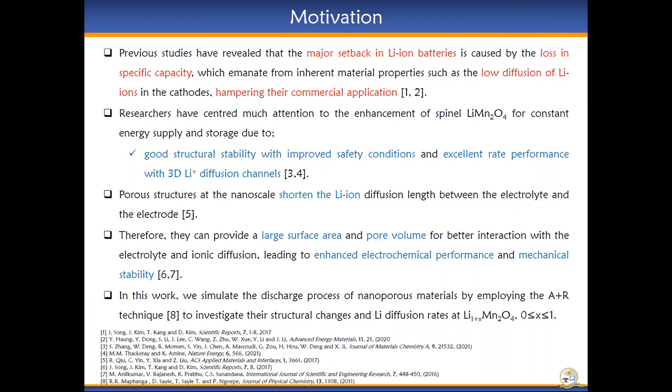Porous structures at the nanoscale have been studied and found to shorten the lithium ion diffusion length between the electrolyte and the electrode. Therefore, they can provide a large surface area and pore volume for better interaction with the electrolyte and ionic diffusion, leading to enhanced electrochemical performance and mechanical stability.